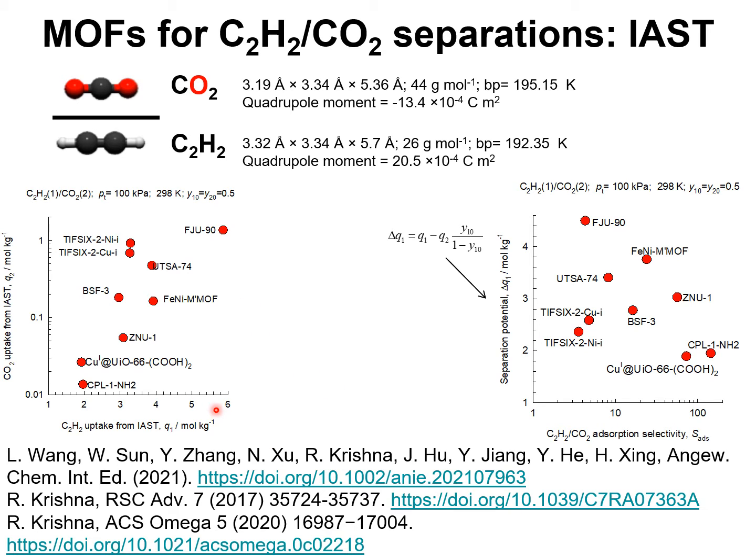These graphs show the IAST calculations for mixture adsorption equilibrium. The left graph here plots the CO2 uptake against the ethyne uptake at a total pressure of 100 kilopascal and temperature of 298 Kelvin and an equimolar ethyne-CO2 mixture.